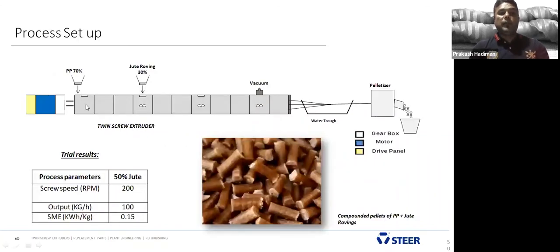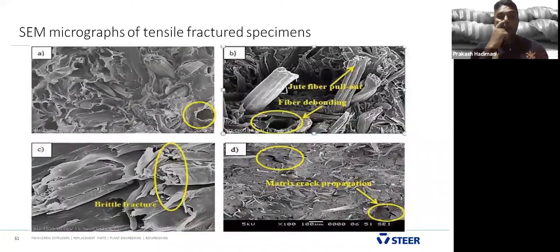We fed polypropylene from the intake and jute, 30% and 50%, from the side feeder, and we were able to manage 50% of jute. In the 40 millimeter we could achieve 100 kg per hour, and these are the pellets. We observed a smooth surface of the pellets. We didn't find any degradation on the pellets. And if you see the morphology, we see better wetting of the jute fiber completely.